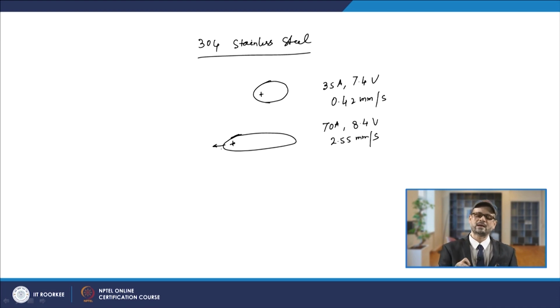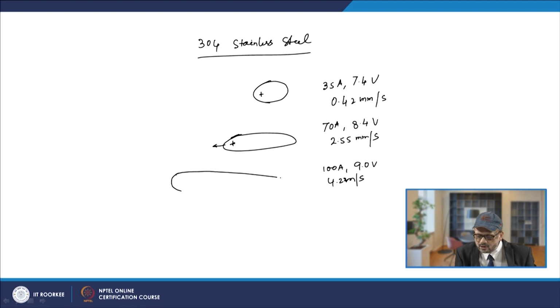So, the pool earlier was elliptical and now it is elongated, and if you further increase the current to 100 ampere, the voltage to 9 volt, and the velocity is further increased to 4.2 mm per second. So, this is the work by Smolik that is reported. Then in that case your pool goes like this. So, the pool will become in the shape of the teardrop.